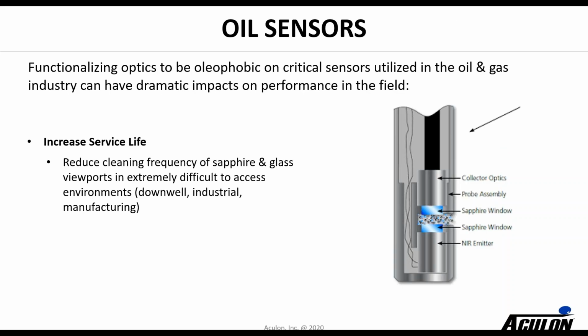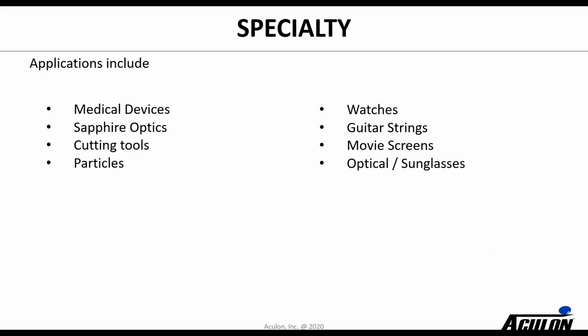Another example would be oil sensors. This could be a sensor that goes down a well and looks at what is going on down the well. They use sapphire because it's a pretty aggressive environment, and sapphire is a very hard, durable substrate. But the problem is that those sapphire windows get blocked by oil and other contaminants building up on the sapphire. So in this case, we treat the sapphire window and allow that sensor to function without having to be brought out and cleaned, which obviously is a time-consuming and costly process.